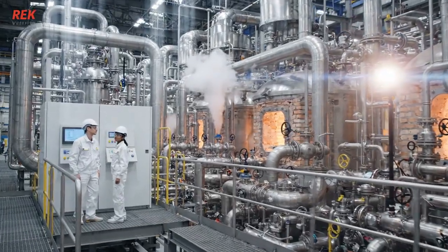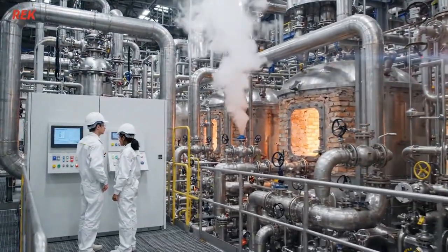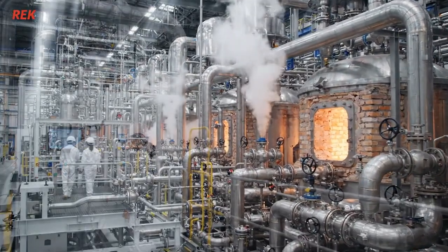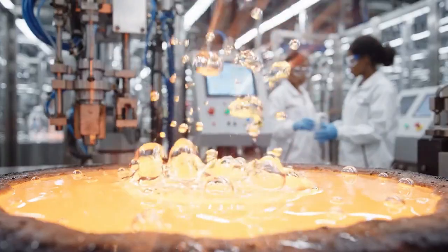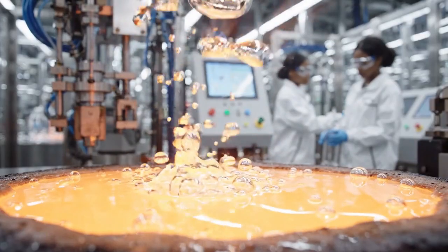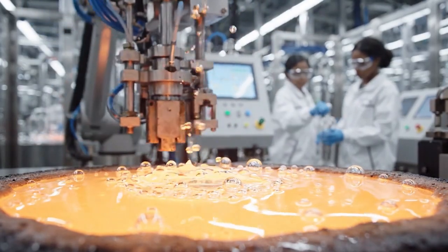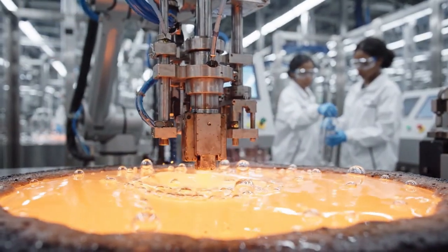Regenerative heat recovery captures over 60% of the exhaust heat and returns it to the combustion process, dramatically reducing fuel consumption. Refining removes the bubbles that would appear as defects in finished bottles. The glass must be perfectly clear and bubble-free when it reaches the forming machines.